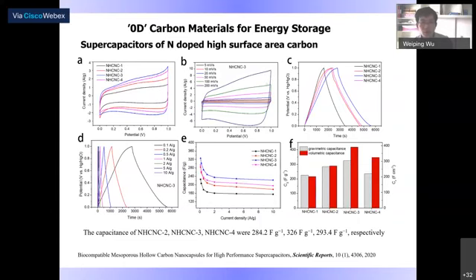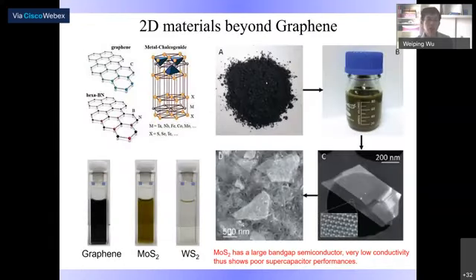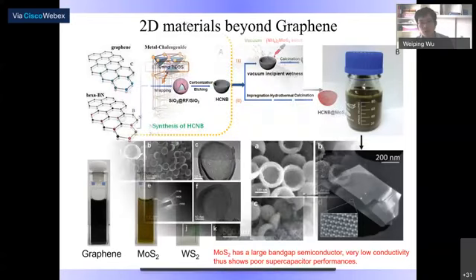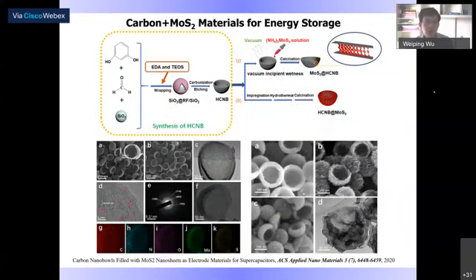Furthermore, I also thought about two-dimensional materials. In this case, I developed a zero-dimensional plus two-dimensional configuration. For instance, MoS2 or WS2 as a semiconductor material has usually been used for optoelectronics, but for supercapacitors it's very difficult to get very high performance using MoS2 or WS2. Therefore, I synthesized MoS2 and WS2 within the space of these carbon spheres and balls. In this case, two types of composite material have been synthesized.